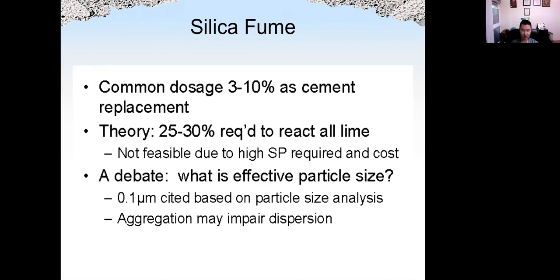The particle size for silica fume we know is very small, but it may stick together. We call that aggregation. So that will make the effective size of silica fume very large, sometimes even larger than typical cement particles. So that will impair dispersion or even generate ASR, because silica fume has a lot of reactive silica. So aggregation of silica fume may just act as the reactive aggregate. So pay attention to that.